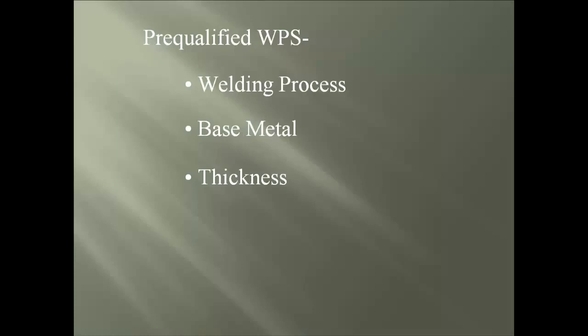The third item is the material thickness, and here the value of the welding procedure could be affected by the different thicknesses introduced, and that is why the pre-qualified weld joints listed in the D1.1 code have limitations on the thickness ranging from 1/8 of an inch and greater. Now is the joint configuration item, which is a sketch that provides table-like values for the accurate requirements covering the process, thickness, and position. The table covers other items such as the root opening, groove angle, and their tolerances for both as detailed and as fit up.